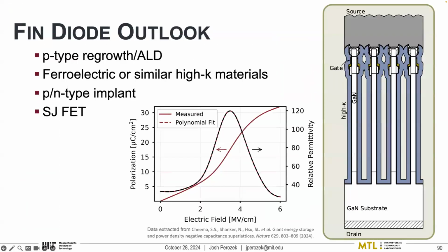And what we can do looking forward, as the growth technology catches up, there might be ways that we can either use regrowth or ALD to incorporate some type of P-type oxide. People have been successfully using nickel oxide as the P-type material instead of gallium nitride. We can look at ferroelectric or other high K materials that in pulse conditions offer these same high permittivities.